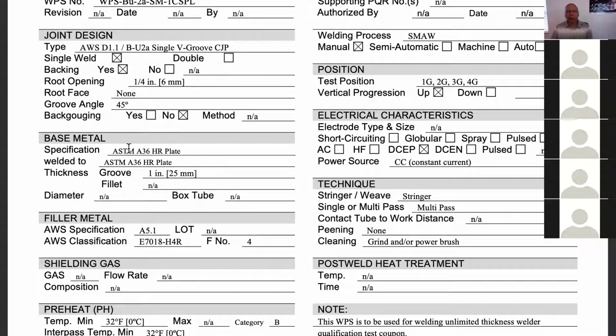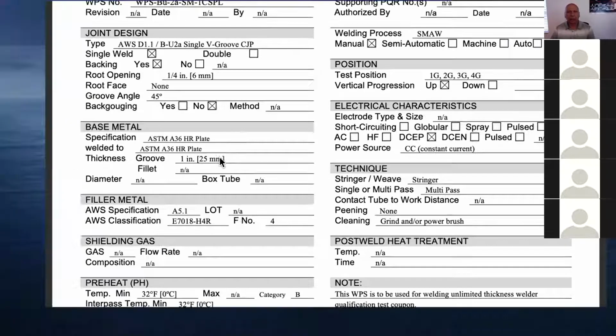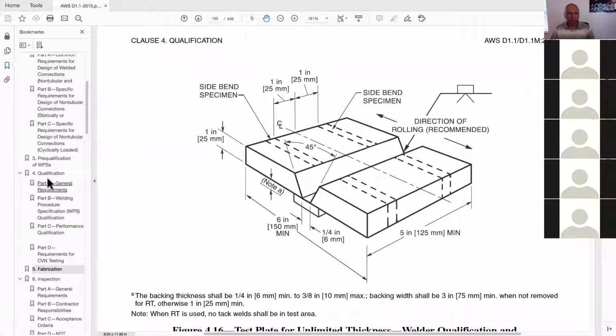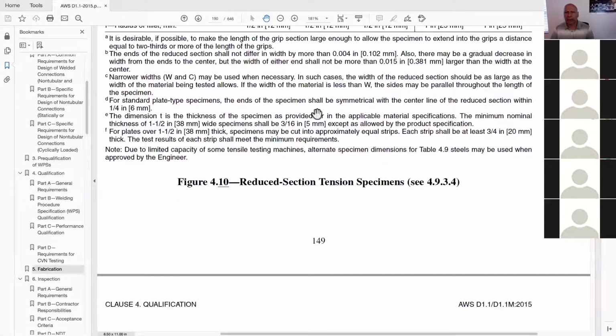The weld's going to be made on ASTM A36 hot roll plate because it is a low yield material that is going to have the elongation required to be able to do the bend test successfully and really be able to determine whether the welder has the skill level or not. We wouldn't make it difficult for a welder and give the welder a material that had a high yield unless we were required by contract. Let's say the customer wanted the welders tested on a higher yield steel. Otherwise, we don't, simply because when we look at D1.1 and we go back to clause 4, the tables in clause 4, that is, we're going to see that the welder qualification ranges